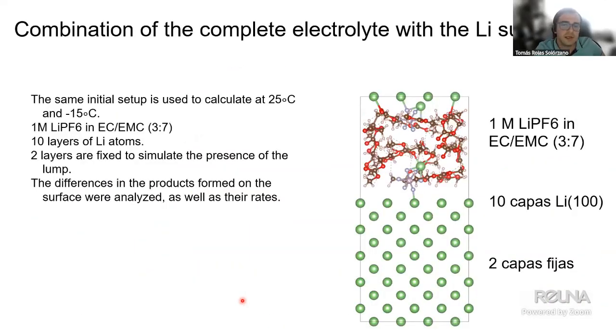Well, in this case, what we did then was model the more complete cell. So we modeled the electrolyte with the three components, LiPF6, EC, and EMC. We do 10 layers of lithium atoms, and we fix 2 layers in between. The reason why we always fix layers in between for most of these cases is to give an effect of the bulk in the anode surface. Right, in the case of a battery, the anode is not going to be 10 atomic layers deep. It's going to be much larger.